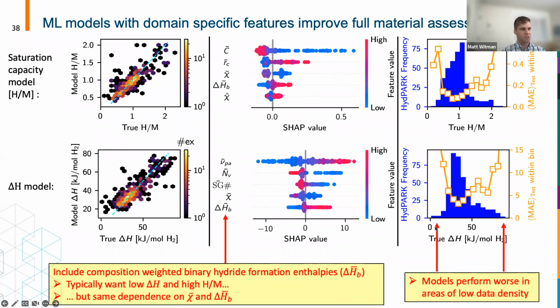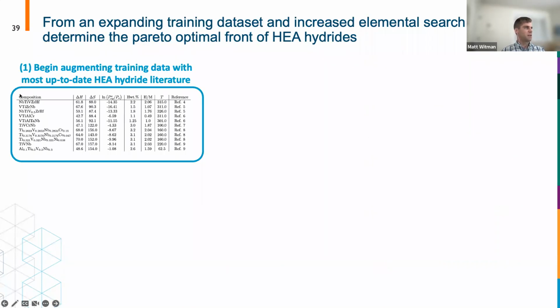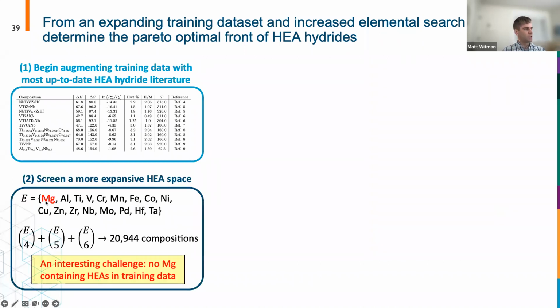And then the other caveat that I want to share with these models is that the HydPARK database has a huge skew in its underlying data distribution. Most materials are peaked around these central values. So as soon as you try and start predicting materials on the very edges of the distribution, your error starts to explode. So that's one limitation of the model. But nonetheless, in this last stage of the project, we've mined as many experimental values of high entropy alloy hydrides as we can from the literature and added that to our training data. We've gone to a larger screening space where we now have an even expanded set of elements including magnesium, which is an interesting challenge because there's no magnesium containing hydrides in this training data.